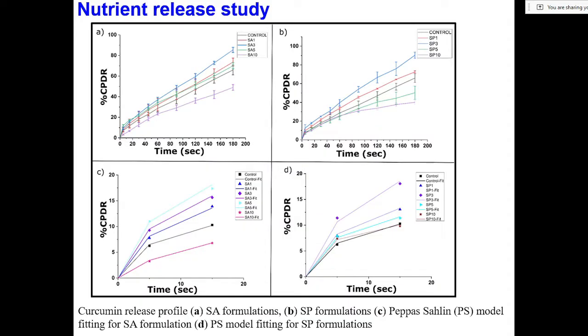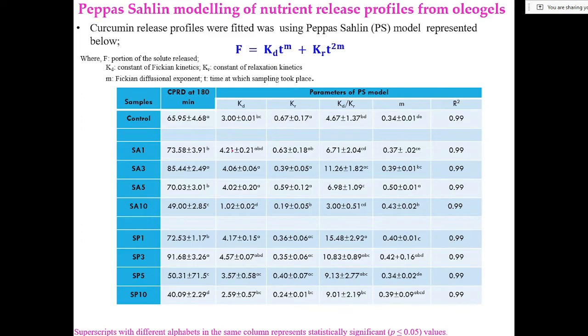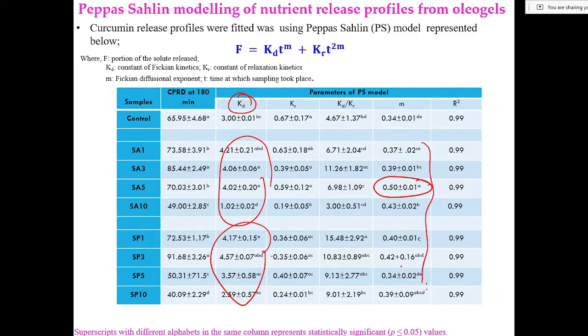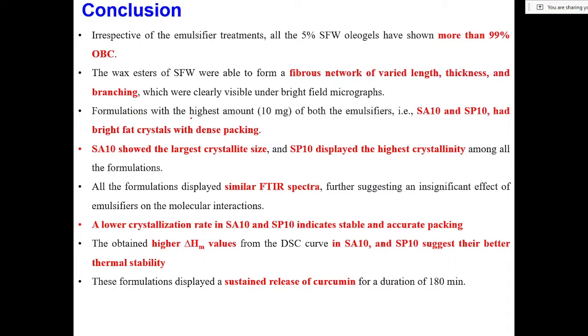Okay, so then we performed the nutrient release study. Over here we used curcumin as the model nutrient, and we got this release profile over here. So this one is for the SA based samples, this was for the SP based samples, and then we modeled the initial part of the release through the Peppas-Sahlin model. So C and D are the model parameters. Again if you see this diffusion parameter, it is changing in a differential way, and looking into what kind of kinetics it was following, except for SA5, the rest of the samples followed Fickian diffusion kinetics.